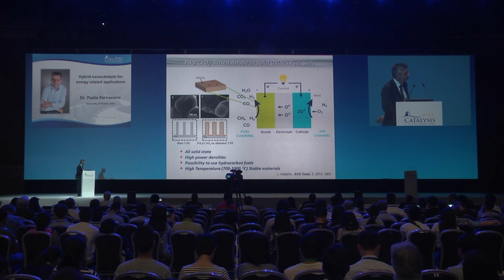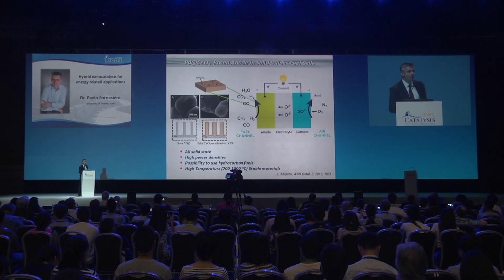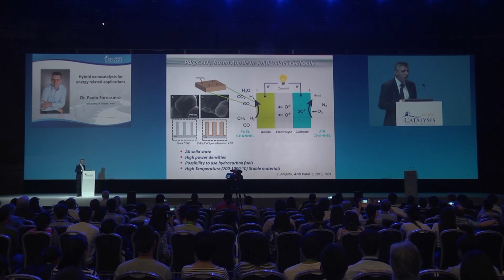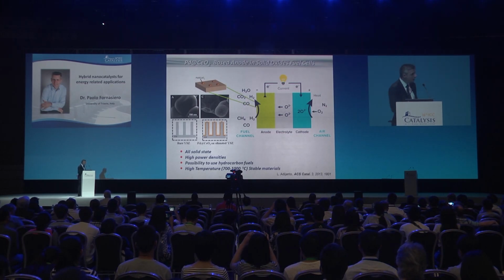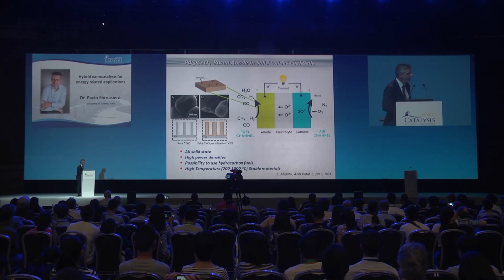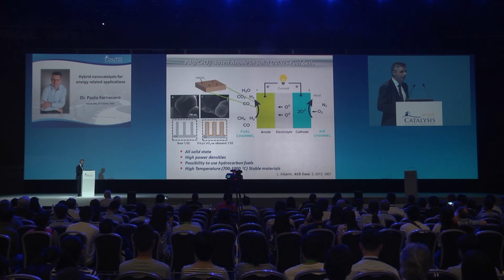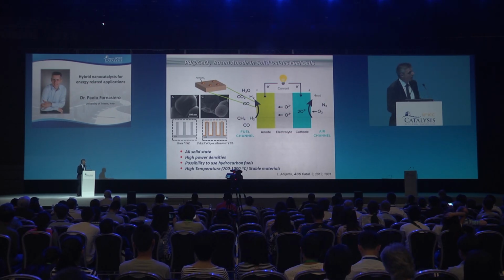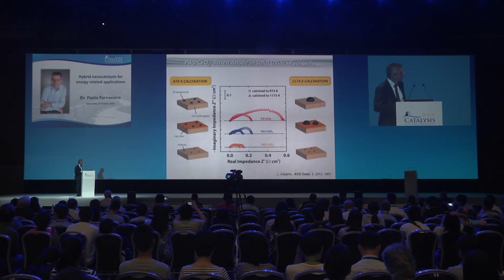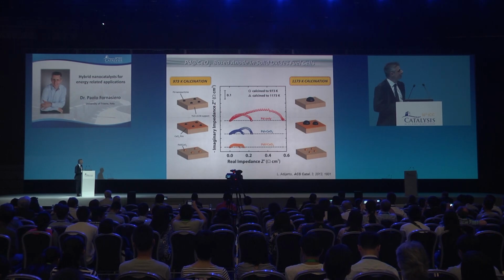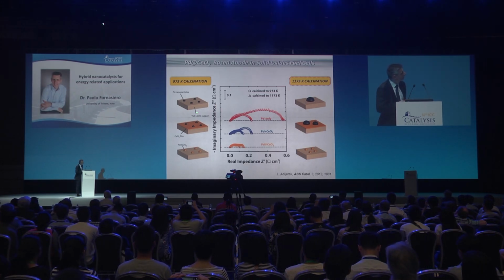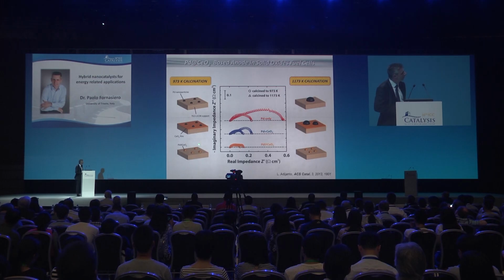And the first type of application we thought of for this type of catalyst was in solid oxide fuel cells, where in the anode you have a palladium ceria catalyst that has to activate the fuel, being methane, hydrogen, syngas, and so on. But the high temperature at which this catalyst operates causes sintering, and so you lose the catalytic activity. And you have to cope with that by adding more and more metal, which is precious, rare, expensive. So we thought that our embedded catalyst has a much higher stability, and we compared the performances of palladium-only technology with palladium ceria prepared in a conventional manner and our system.